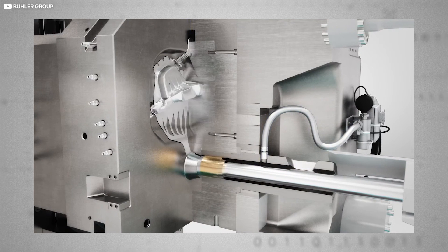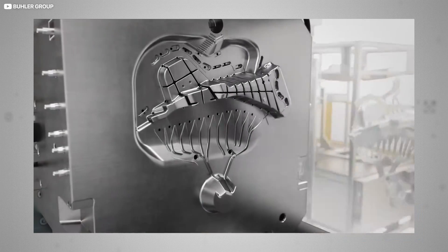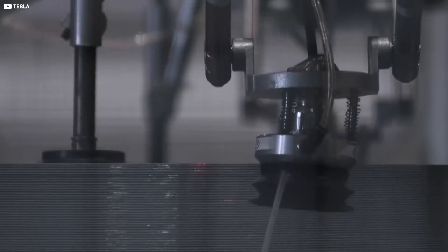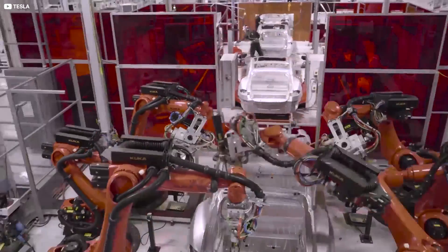When full, the mould is then opened and cooled to 400 degrees Celsius. The newly shaped metal part is then removed by robot to a quenching tank at a chilly 50 degrees Celsius to help it set. A mechanical trim press cuts off any unhelpful excess to within meticulously established tolerances, shunting the waste back to be recycled elsewhere in the process, and the whole thing is x-rayed to ensure it's roadworthy. Final trimming is carried out by lasers, then conventional drills go to work getting the final piece ready for attachment to the car.